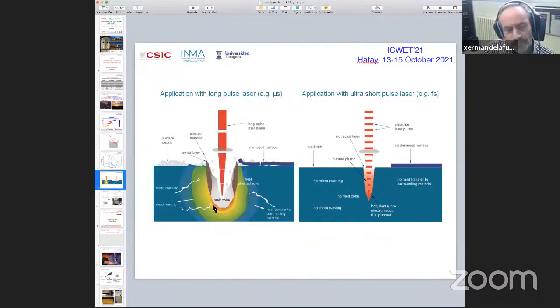One aspect of pulse duration, which I talked about before, just very briefly, is that if you use long pulse duration, you can usually expect to observe melting and a lot of heating around the spot where the laser is incident. While if you go to very short pulses, and at the extreme to femtosecond pulses, then heating will be a minimum, and you can get other types of phenomena, far away from equilibrium. We may see some of it.